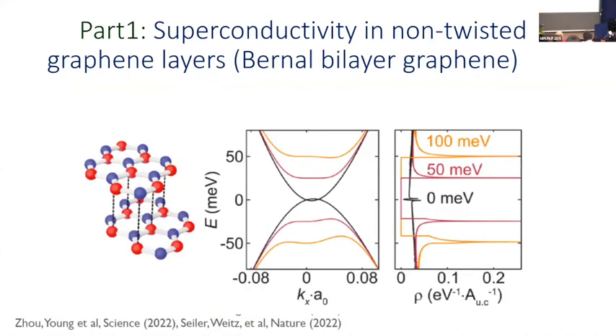There are two examples and I will try to show commonalities between them. One is Bernal bilayer graphene — very popular now as an offshoot of twisted bilayer graphene. It's AB stacking where the atom in the top layer is positioned exactly in the middle of the hexagon in the lower layer. This material was studied extensively back when graphene was studied without twisting, and there's a famous story about the quadratic band touching.